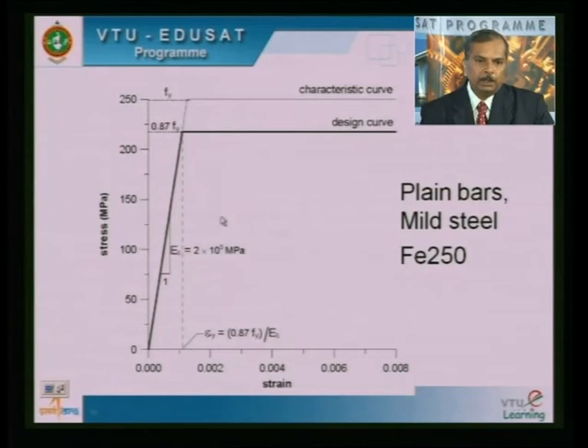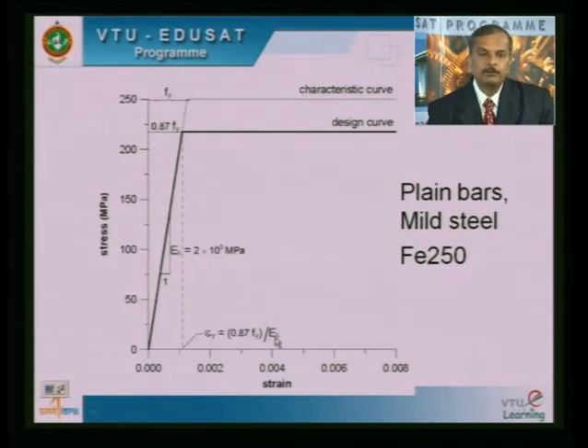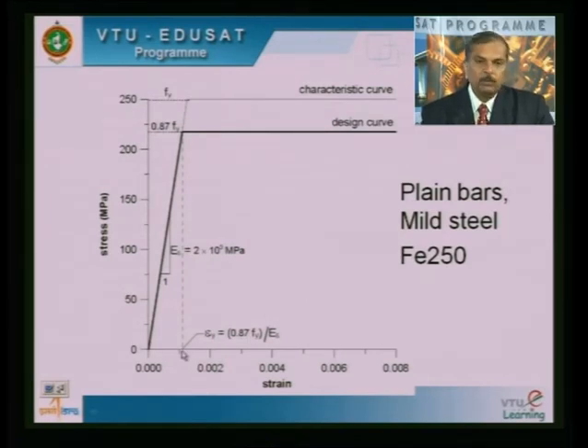Means these mild steel will yield at a strain of approximately 0.0011. So that can be identified as 0.87 fy divided by Es, where fy is 250, 0.87 into 250 divided by the Young's modulus of steel, 2.0 into 10 to the power of 5. If you use it, you get a strain of about 0.00109 and very close to 0.001, in other words 0.1%. So 0.1% being the yield strain of steel, but when the concrete is subjected to a maximum strain of 0.002, definitely your mild steel has yielded with a yield stress of 0.87 fy. So that is the design strength of steel in case of mild steel bars.